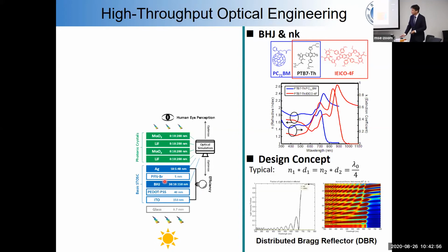So the blue one itself is already a basic semi-transparent OPV. But now we can try to introduce a distributed Bragg reflector photonic crystal. The function of that is, at this interface, we reflect the infrared light back so that we improve the infrared harvesting, but we allow the visible light to pass through it. Increase JSC, maintain similar transparency.